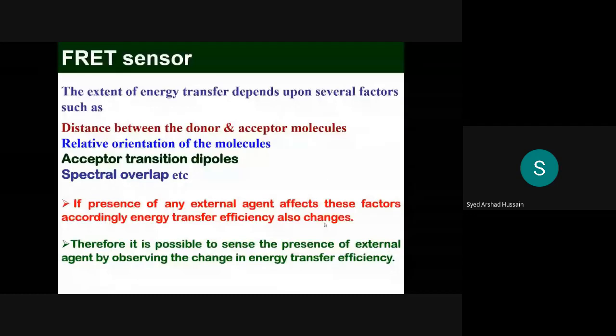But this is, you know, two fluorescence systems. When you design optical sensors using a single fluorescence system, your fluorescence intensity increases or decreases, and just by observing the change, you can have an idea about the sensing. But here, there are two systems. For the donor, fluorescence will decrease because it's giving energy to the acceptor. For the acceptor, fluorescence will increase. So it's a ratio between the fluorescence of two molecules. And in this way, if there are any external perturbations or contamination, etc., it automatically minimizes because it measures the ratio between two fluorescence intensities.